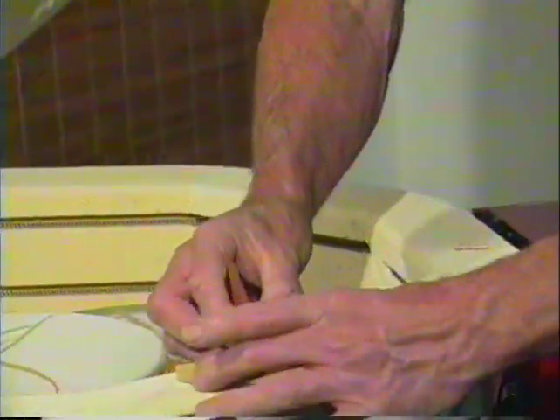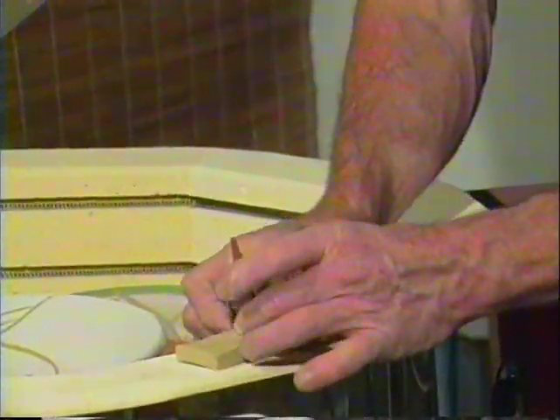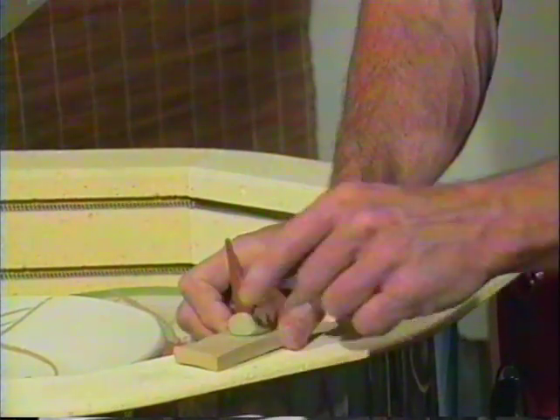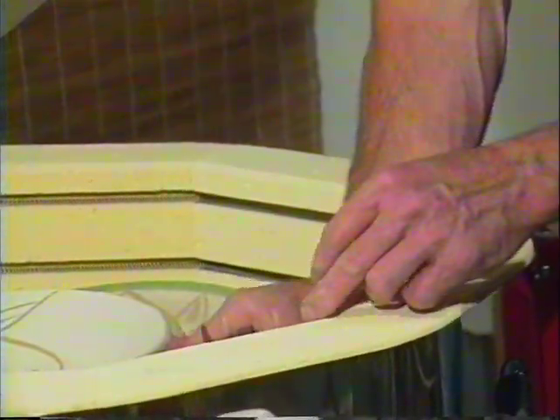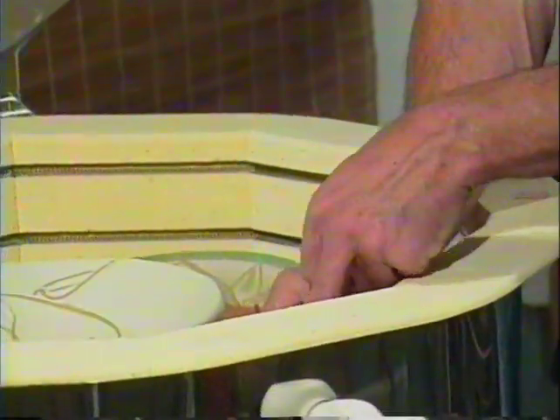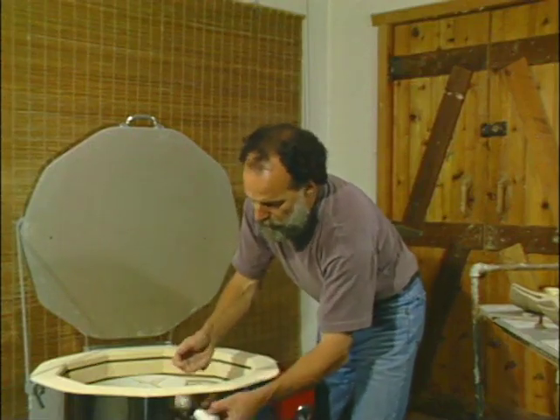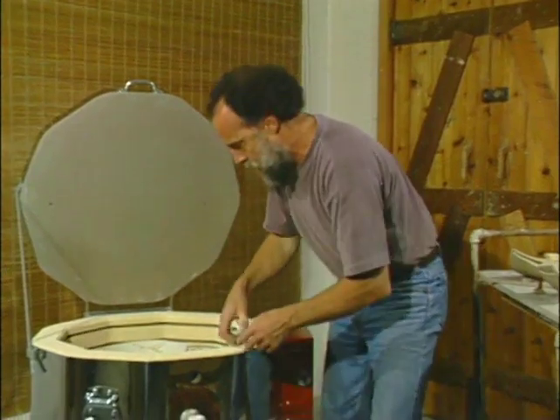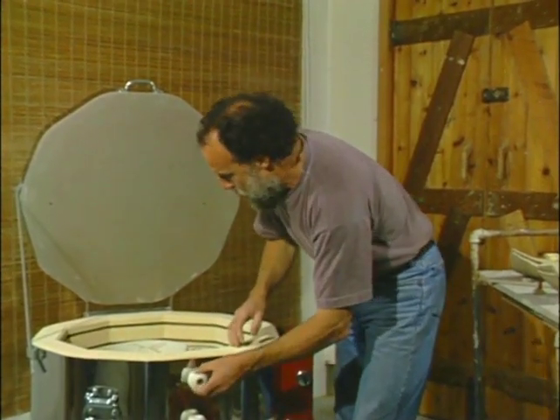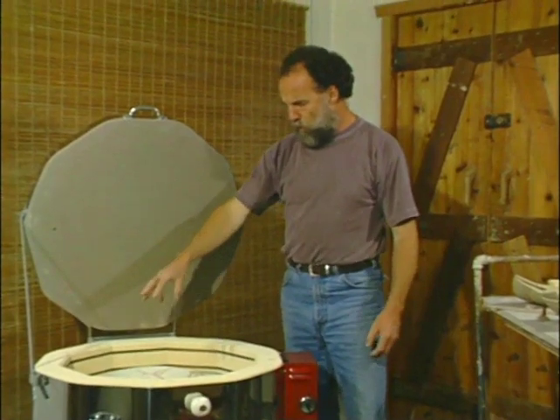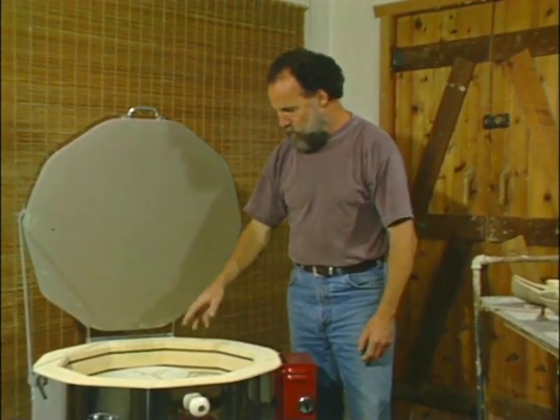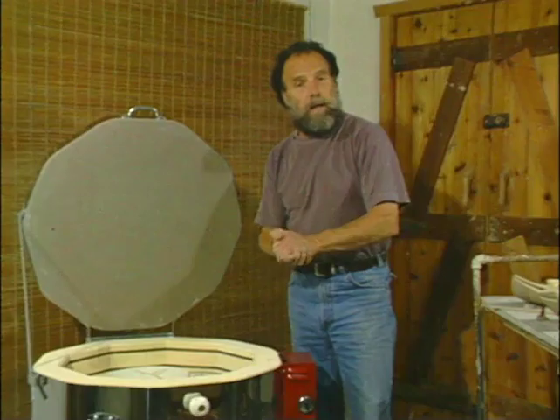Okay, so we're going to place it on a little pad of clay so that when it falls and droops, it won't fall down onto the kiln shelf and maybe stick to it. And we're going to place it so that we can clearly see it through this spy hole. Slightly to one side of your field of view so that as it melts, it falls across into your field of view. Yep, we can see it quite nicely. Okay, so I'll put in a few small pots over here to fill up the spaces that remain, close the lid, and we're ready to begin the bisque firing.